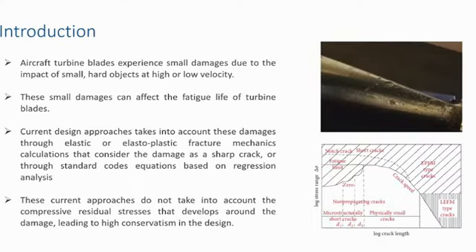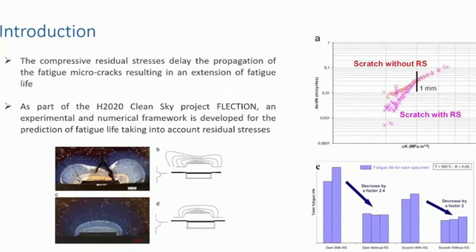The main objective of this European project is to predict the fatigue life of damaged Inconel 718. The industrial application is that Inconel 718 is used in aircraft turbine blades, which are affected by small damage during their service life, caused by small objects that impact at high velocity, or during handling and repair operations, like a tool dropping on a turbine blade. In order to take into account those small damages at the design stage, linear elastic fracture mechanics approaches are used, which do not take into account the compressive residual stresses under the damage. So they are very conservative design.